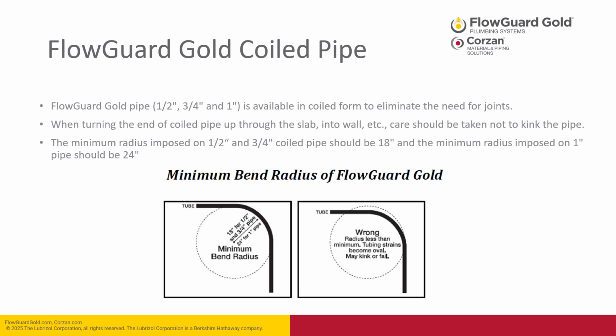When turning the end of coiled pipe up through the slab into a wall, care should be taken not to kink the pipe. The minimum radius imposed on half and 3/4 inch coiled pipe is 18 inches, and the minimum radius imposed on 1-inch pipe is 24 inches. If the pipe is bent more tightly than that minimum radius, the strain on the tube will cause it to deform, which may result in kinking or eventual failure.